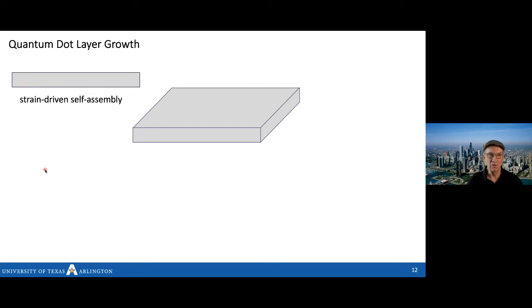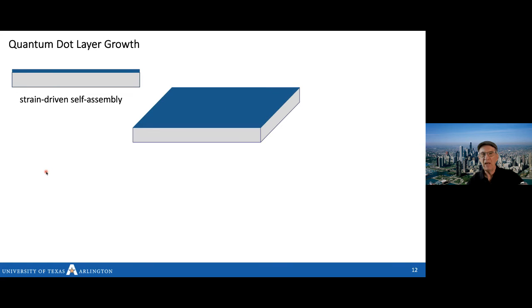It's not necessarily true. But we use strain above the level that's accommodated to force the growth of quantum dots. And it does it like this. When we start growing the first atomic layer, the blue material you see is a larger lattice, and it's growing on a substrate that's smaller lattice. The very first few atomic layers just grow layer by layer. You know, they spread out and even out, and then when the next layer comes on, it starts to do something different. As the strain accumulates, it causes it to grow in three dimensions instead of two.